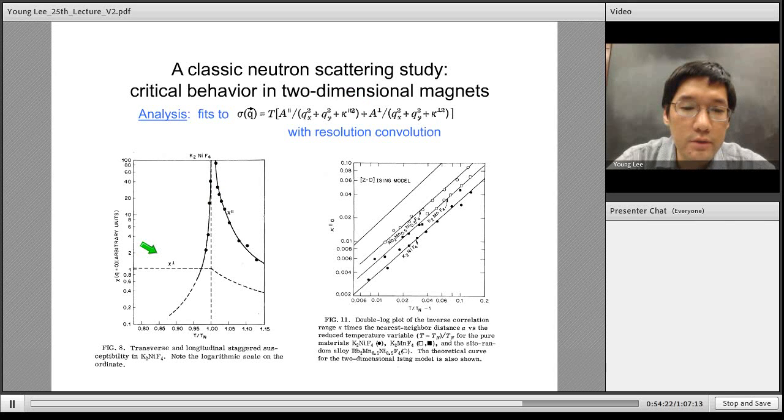And it's the longitudinal susceptibility that they now plot as the filled symbols. That is the part that should have this Ising criticality and have the divergence as you cool down. That's clearly seen, the divergence as you approach from below. And there's also clearly this asymmetry in the prefactors for these divergences, as we've seen in Landau theory, but now this is more closely following the 2D Ising model.